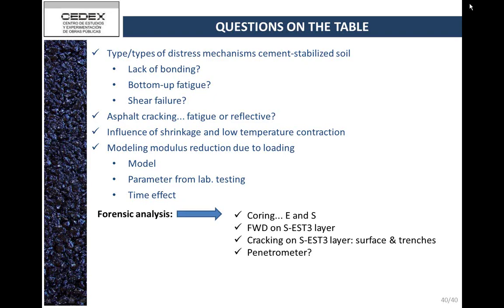Yes. But what we have seen in the test track is that at the beginning of the test, when the stiffness of the cement-treated layer is very high, there seems to be a bit of debonding. But then, as that stiffness goes down, the debonding seems to disappear and the situation is closer to full bonding. Is that compatible with what you said?